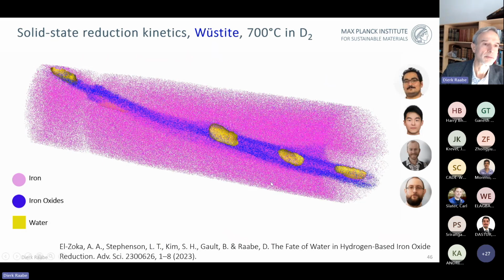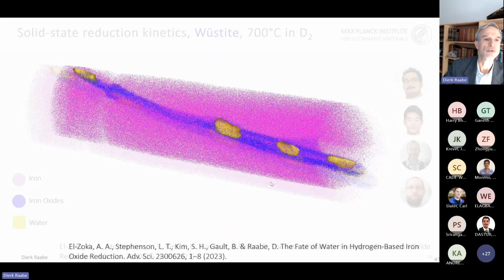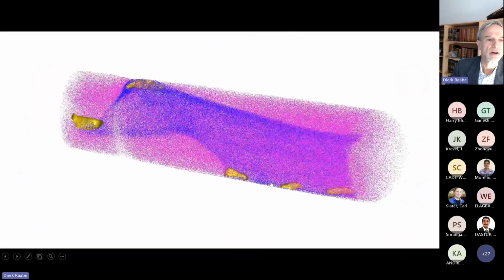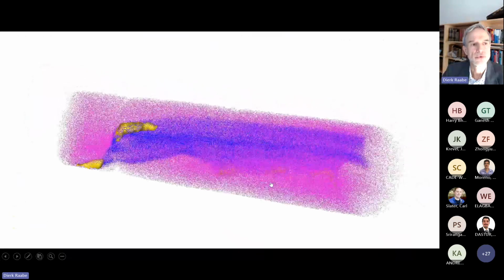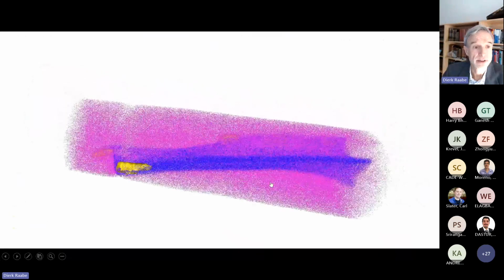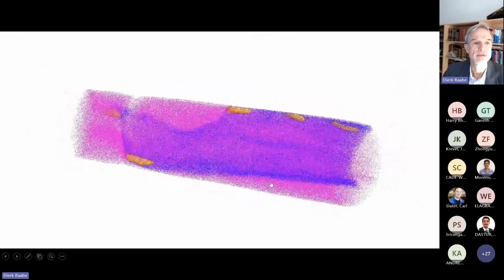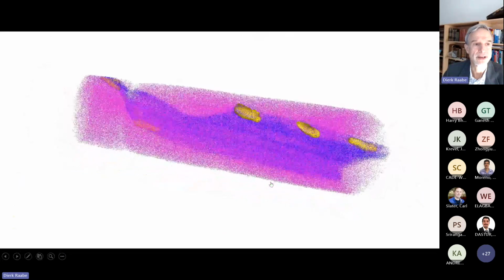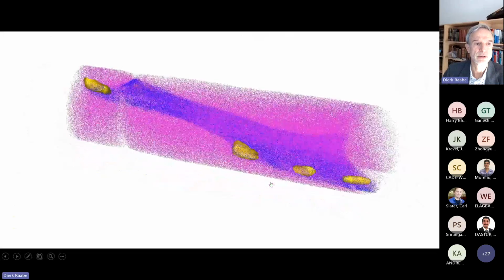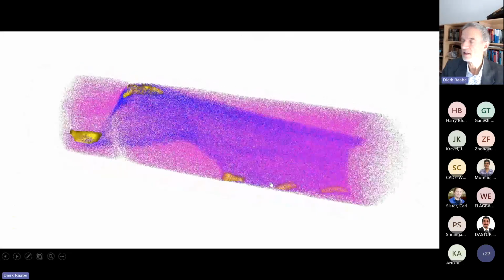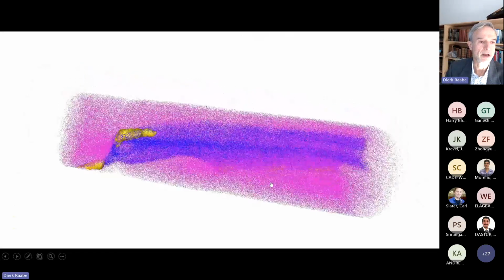So that gives us a better insight, and maybe when I can run the movie, a better insight of where and how the water is formed and stored inside of the material at a very, very early stage, and how it is connected to the formation of the pores. By the way, when you do that here with the atom probe, you are chemically very sensitive.